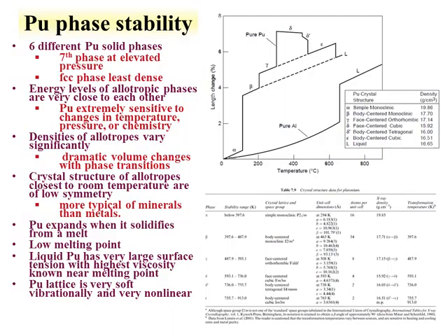All these levels are close to each other energetically, so that's why they can be reached through just heating the sample. Then the densities of these phases vary dramatically. The data is shown here, where the most dense phase is the alpha phase, which is close to 20 grams per milliliter, and the least dense phase is this delta phase, the face-centered cubic, the FCC phase, where you get a little over 15 grams per milliliter.